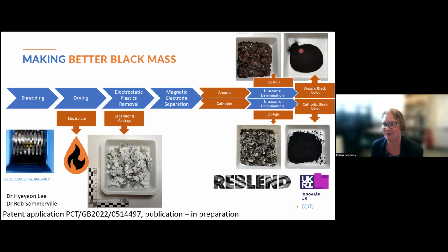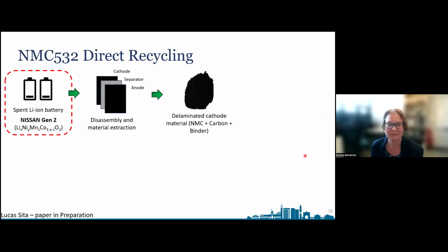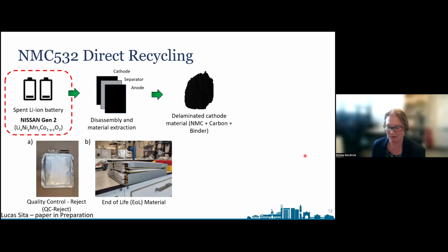So mainly graphite in the anode and mainly the cathode material in the cathode, whether it's lithium iron phosphate or NMC. We've got some examples using NMC materials, which is a Gen 2 Nissan Leaf, where we've disassembled a module, taken out the pouches, and put this through a shredding process. We've also compared quality control rejects, which is straight from the manufacturing line, where the cells have been rejected from a quality control process, and also an end of life from the module.